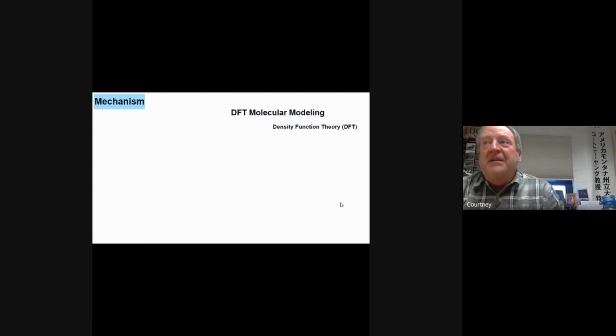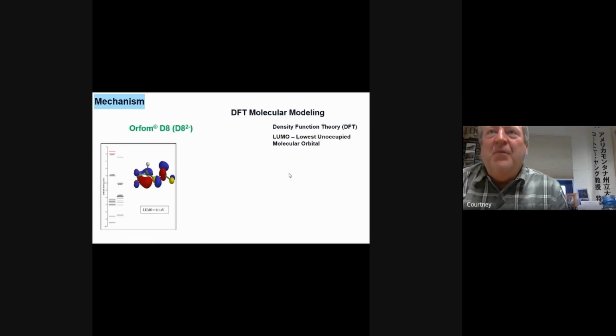Okay, so the other thing that we did was we went in and decided to do some modeling by density functional theory. I'm not very good at this, but from what I understand, you take the lowest unoccupied molecular orbital, and so all these orbitals that an electron can occupy are occupied. The next one that's up there is the lowest unoccupied. So we're going to take a look at that energy level.